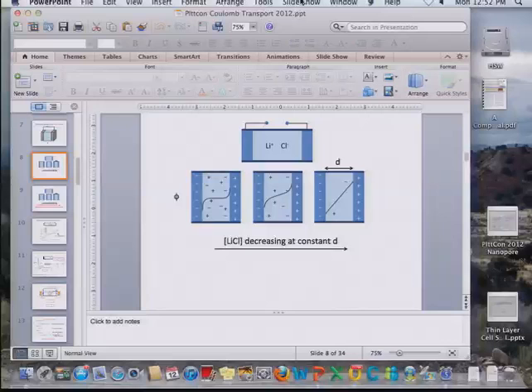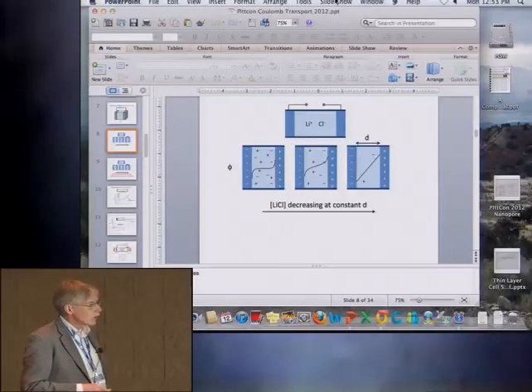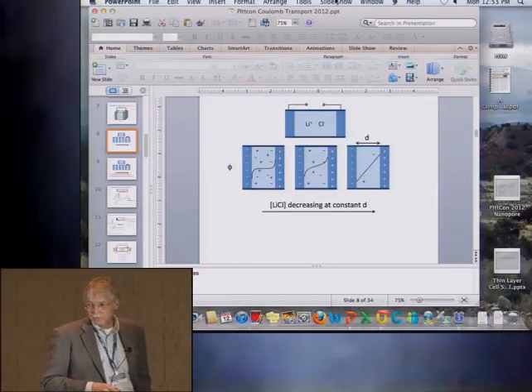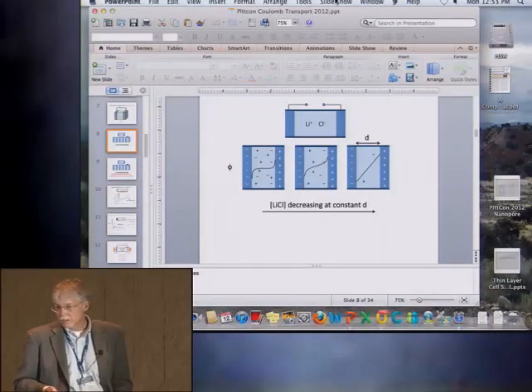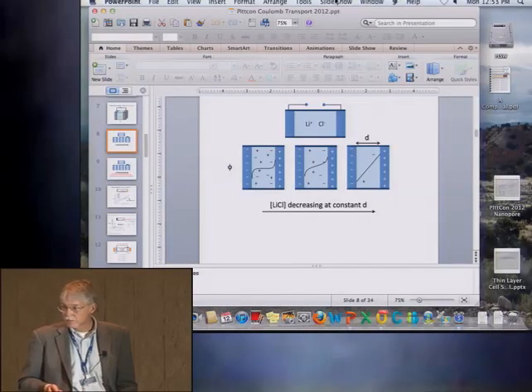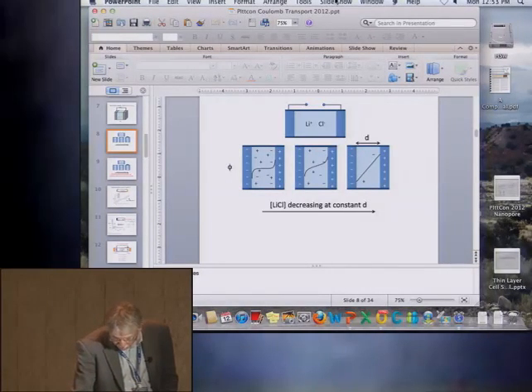Okay, so what do you expect for the electrical potential profile? Well, if you just think about decreasing the concentration of lithium chloride between two electrodes, starting at 1 molar, 2 electrical double layers, well separated, then you start decreasing the ion concentration, and eventually you get to something that looks like a capacitor. If you take all the ions out, it's simply a capacitor with a linear potential profile, right? That's not what we're doing here.